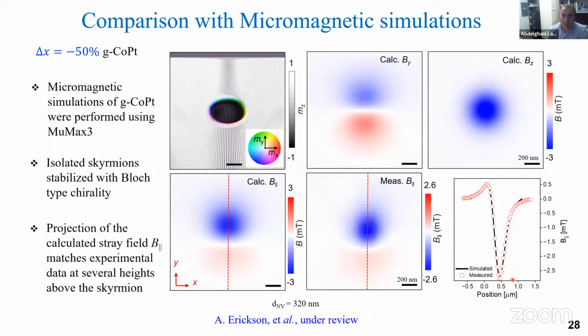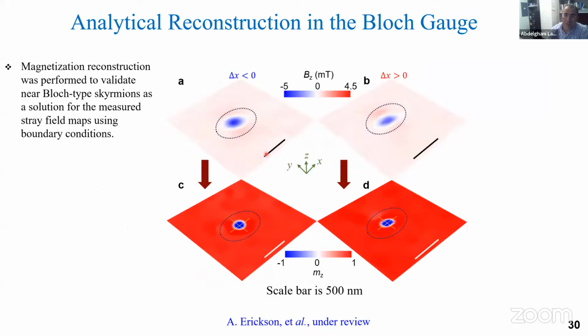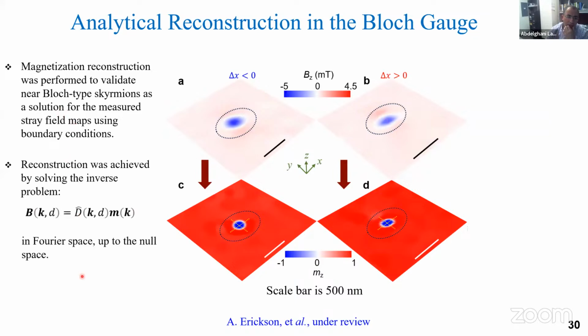So while looking at the orientation of the spins, one can know this is Bloch type, but the Kovalev group in particular did a detailed analysis going from the stray field maps, in this case for a given skyrmion, let's say a negative gradient or positive gradient sample. In principle they reconstruct the magnetization by using the so-called inverse propagation protocol. Knowing the stray field, one can get the magnetization by posing some boundary condition